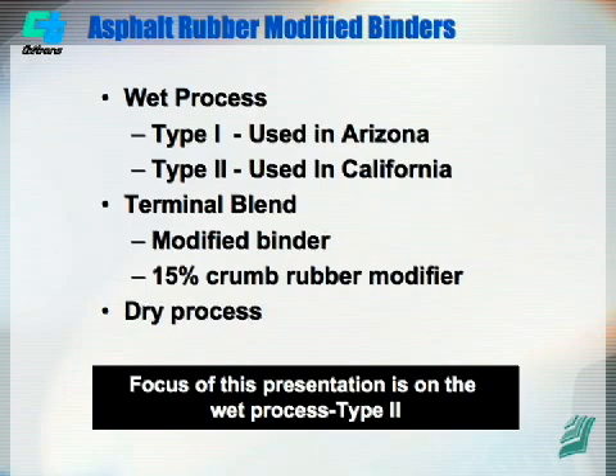However, based on our field performance in California, we decided we were going to use type 2, and we've done that for asphalt rubber hot mix and also for seal coats, chip seals. This experience is based on the performance of the projects. We are also looking into type 1 and type 2 at this moment for seal coats, based on the recent performance of asphalt rubber chip seals in some of the warm districts.